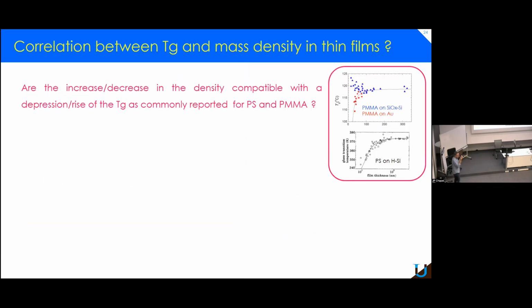Obviously, when you think about density, people working on polystyrene or PMMA have measured the glass transition. And what people are finding all the time is that the glass transition of polystyrene decreases when the thickness decreases, and for PMMA it's the contrary. So how can we rationalize those results with the fact that the density is increasing for PS and the glass transition is decreasing? It's something that is difficult to understand.